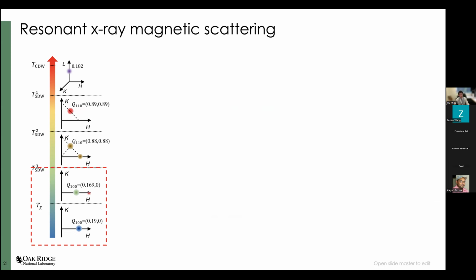Below 12 Kelvin, the four-fold rotational symmetry is broken, and you form a single Q helical spin density wave. And then if you further cool to around 11 Kelvin, you're going to have another transition from a single Q helical to another single Q helical, but the wave vector changes slightly. So our initial interest for this study is why the system wants to change the Q, why it cannot stay just at this Q. So that's the real motivation for the magnetic study.